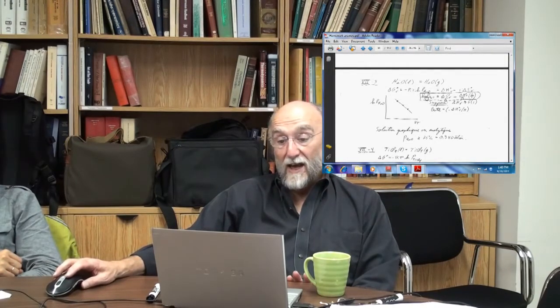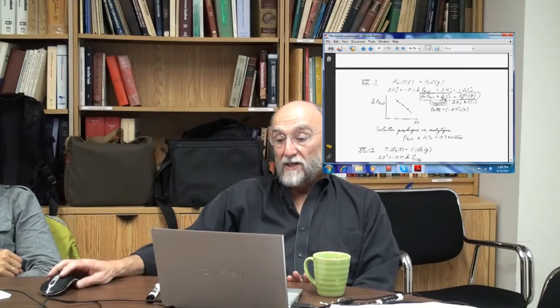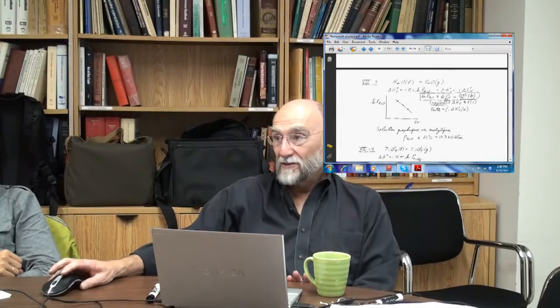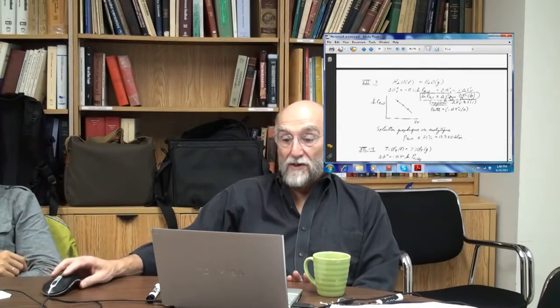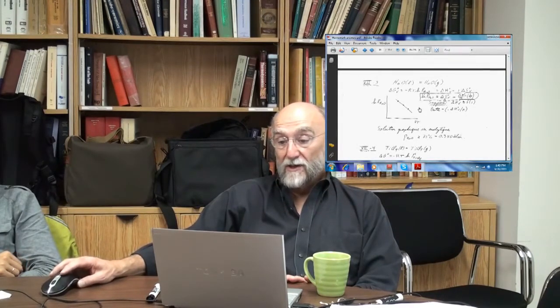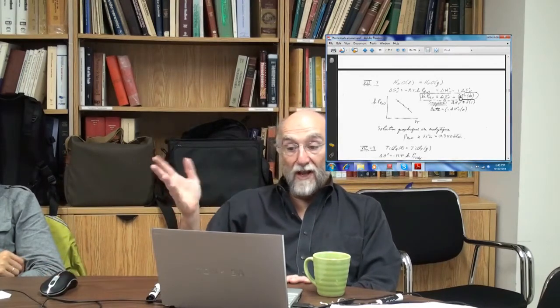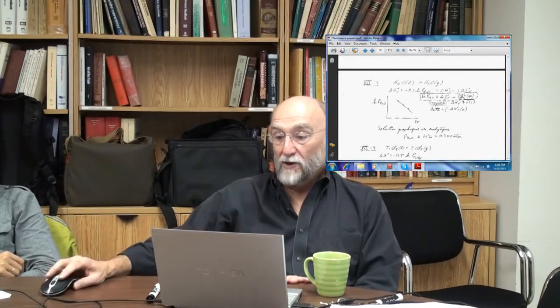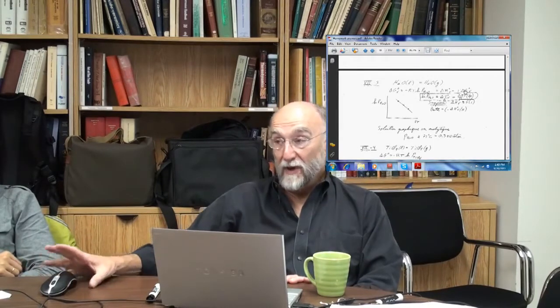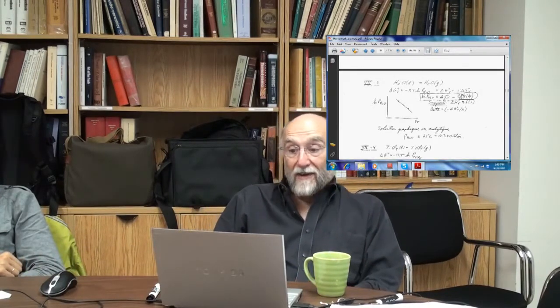It's the same thing, and I plot ln vapor pressure versus 1 over T, and now the slope is minus delta H over R and the intercept is delta S over R. It's the same. Or this is just the Gibbs-Helmholtz equation, d(delta G over T)/d(1 over T) is delta H. So if I plot log vapor pressure versus 1 over T, I'm going to get something pretty close to a straight line, because delta S and delta H of vaporization are more or less temperature independent. Of course, it isn't exactly a straight line because delta S and delta H depend on the temperature, but over 25 degrees, the heat of vaporization and the entropy of vaporization don't vary that much.